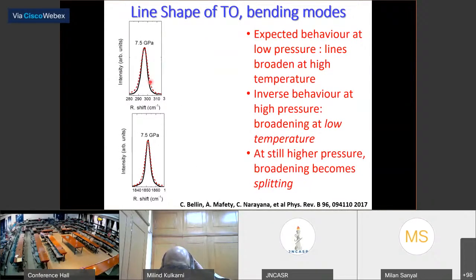Now, let us look at the line shape of the transverse optic mode as well as the bending mode. When we look at the transverse optic mode, you realize that at a given pressure, as you increase the temperature, the width increases. The dark line is for 100 Kelvin and the dotted line is room temperature. You can see the width increases. That is normal behavior.